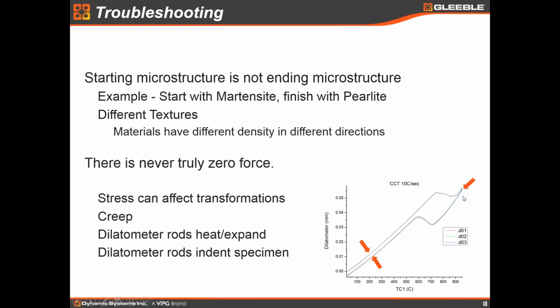In fact, the arrow here at the upper right of the attached graph, I suspect is a little bit of creep that has happened while holding at high temperature, where the quartz rods, which have a single point contact with the sample, have either indented the sample a little bit, or the quartz itself has indented a very minute fraction and creeped a little bit in the sample. I will mention I've seen examples that are much worse than this, and the temperatures of these transformations are still quite good. So a little bit of creep doesn't really affect those transformation temperatures very much. It may not be something to worry about, but if you're looking for a really pretty graph to put into a publication, it might be something to be aware of. The other thing is that the dilatometer rods themselves will heat and expand a little bit.